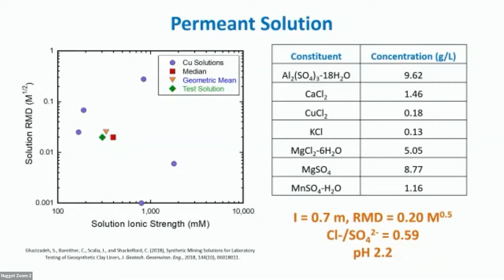And for bentonite materials, there's really 2 key variables that influence whether they swell and their hydraulic conductivity. One, the solution ionic strength, how concentrated it is. And then this other parameter called RMD, which is the ratio of monovalent to polyvalent cations, essentially a relative measure of the relative abundance of monovalent and polyvalent cations. And this solution was about 700 millimolar, so pretty concentrated. It's got an RMD of 0.2. RMD has weird units of molar to the 0.5, but that's a divalent solution, not surprising given the geochemistry of the constituents in our mixture.